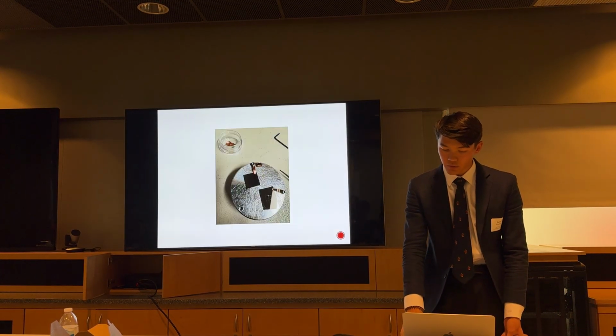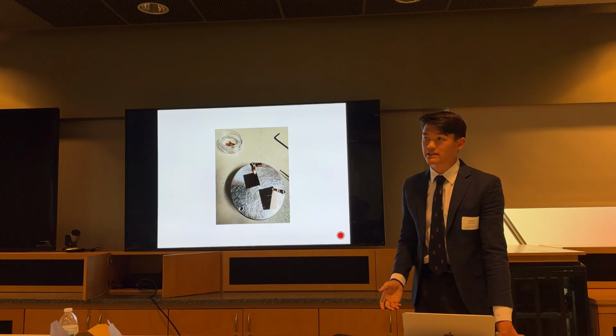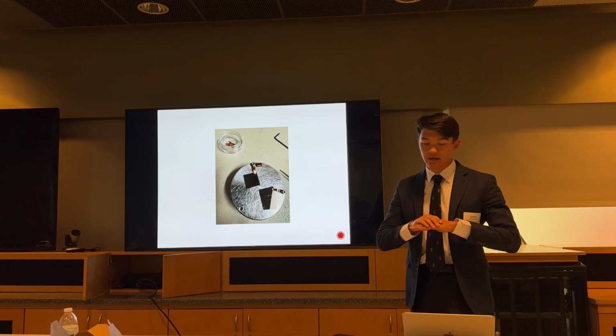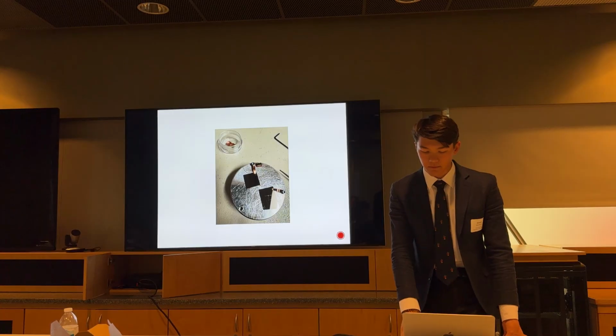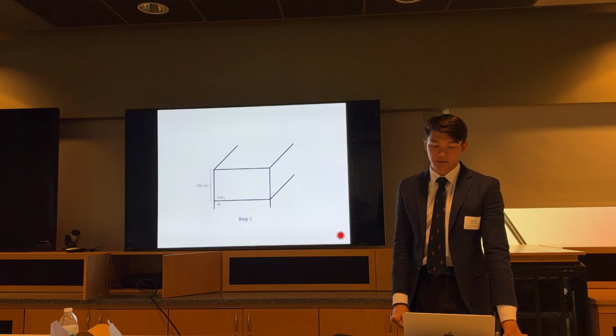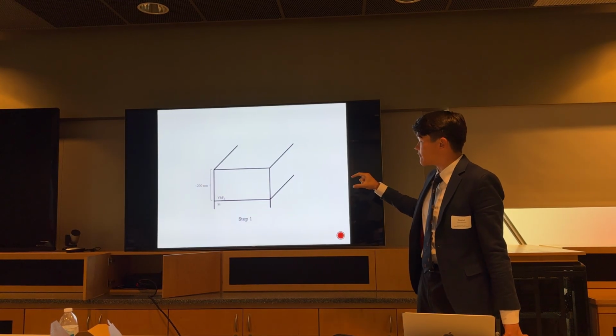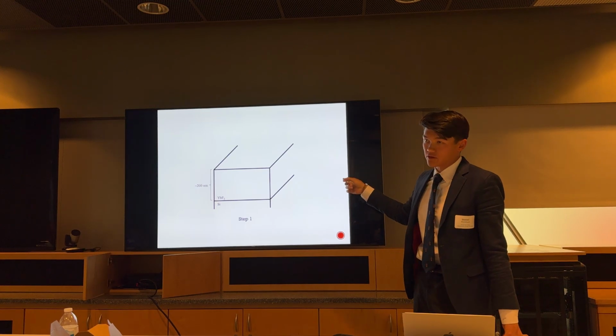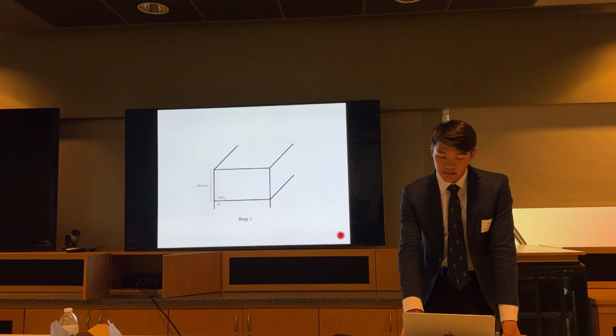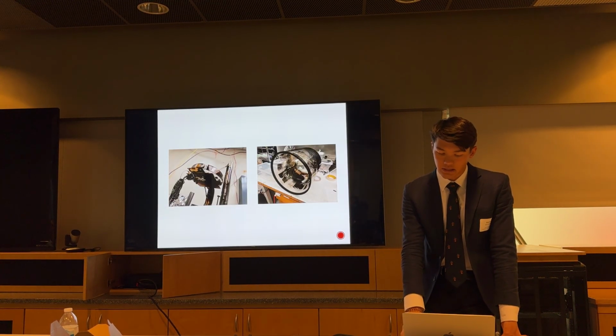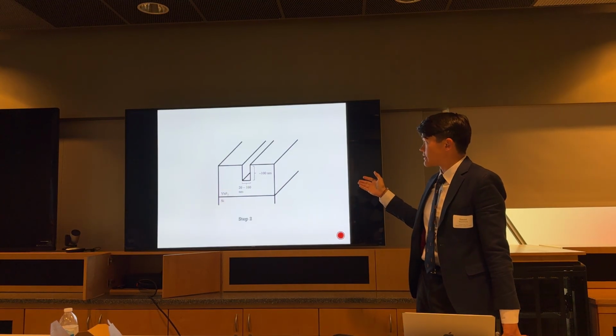To begin with, we do still start with silicon, not because we need its semiconductor properties, but just because it's the nicest, flattest material. And on top of that, we deposit a few hundred nanometers of ytterbium fluoride. And we do this with physical vapor deposition in a setup that looks something like this. And then we create this trench.